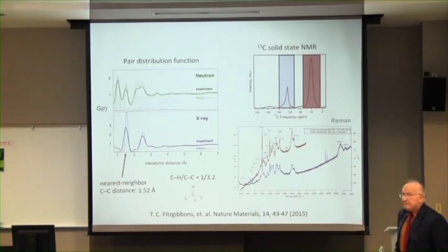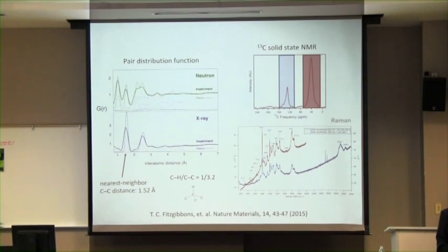Now they threw at this every technique of characterization that you can do to an amorphous material. It doesn't dissolve in anything, so you can't do an NMR. It's not crystalline, so you can't do the crystal structure, but you can do diffraction, and they did both neutron and X-ray diffraction, and you can do an analysis. It analyzes for CH approximately. You can also do C13 solid state NMR on this. And this is the region of sp3, like 4-coordinate carbon. This is 3-coordinate carbon. It's mostly 4-coordinated. There's a little bit 3-coordinate.